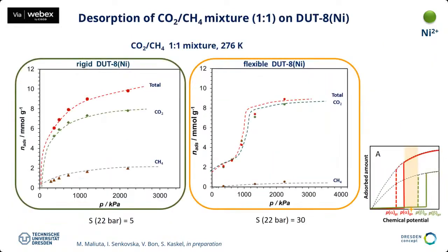So you have a huge gain in selectivity, and you see this also not only for the pure gases, but also for the one-to-one mixtures. Basically, when you compare the selectivity, in a one-to-one mixture, you have CO2 and methane entering the rigid DUT-8, because it's rigid all the time. But the flexible system basically only takes up the CO2. Almost the total gas that is taken up is only CO2, while the methane is not taken up.